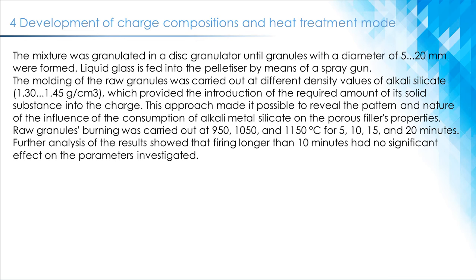The molding of the raw granules was carried out at different density values of alkali silicate, 1.30 and 1.45 g/cm3, which provided the introduction of the required amount of its solid substance into the charge. This approach made it possible to reveal the pattern and nature of the influence of the consumption of alkali metal silicate on the porous filler's properties. Raw granules were burned at 950, 1050, and 1150 degrees Celsius for 5, 10, 15, and 20 minutes. Further analysis of the results showed that firing longer than 10 minutes had no significant effect on the parameters investigated.